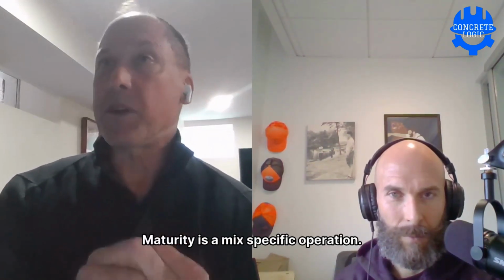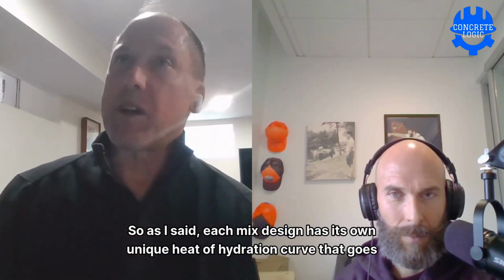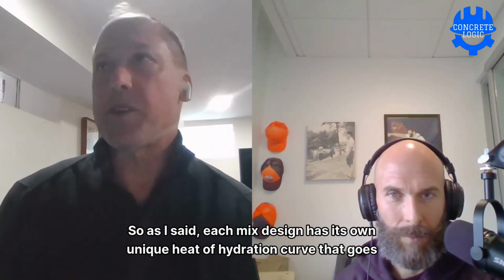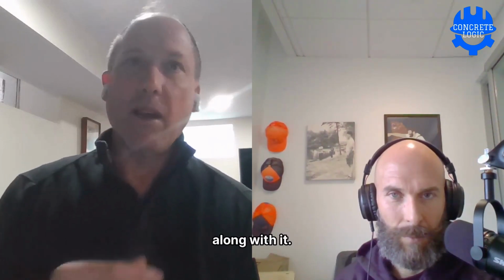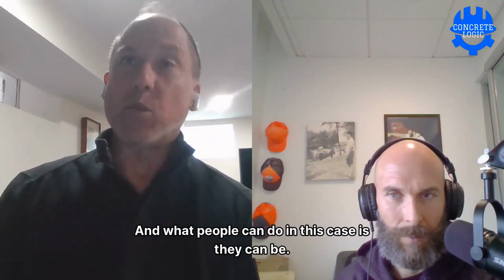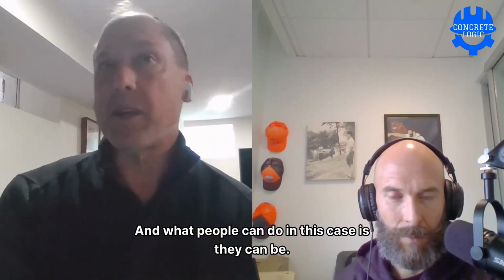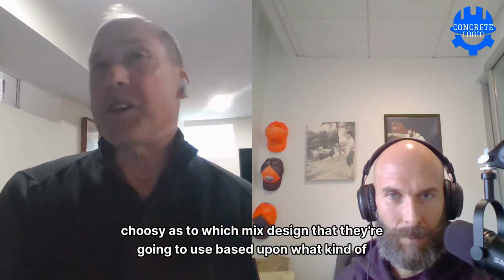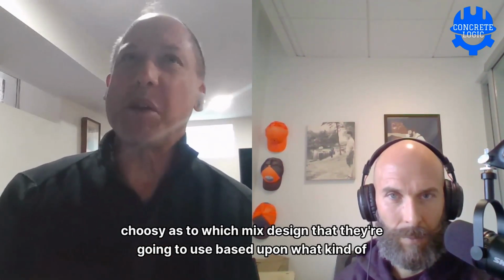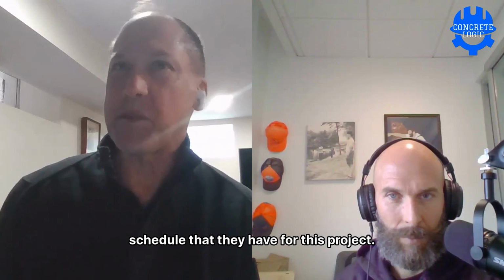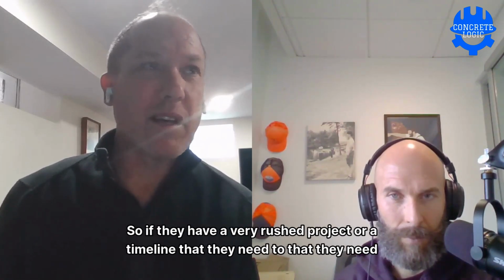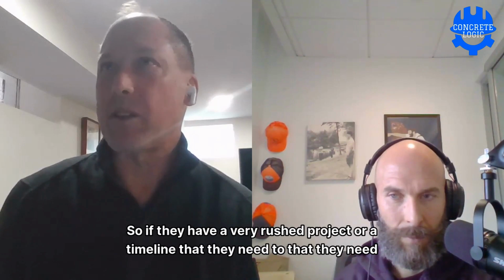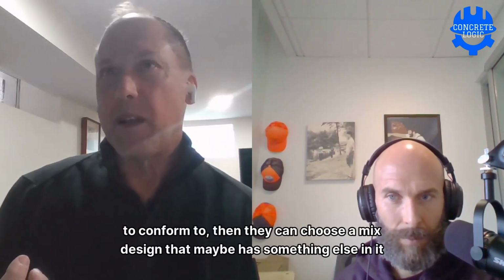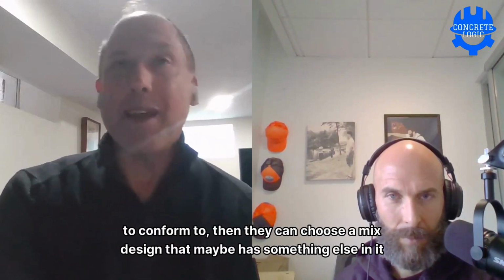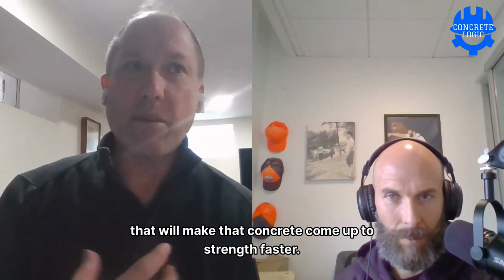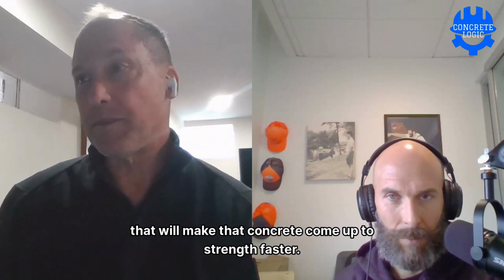Maturity is a mix-specific operation. As I said, each mix design has its own unique heat of hydration curve that goes along with it. What people can do in this case is be choosy as to which mix design they're going to use based upon what kind of schedule they have for this project. If they have a very rushed project, or a timeline that they need to conform to, then they can choose a mix design that maybe has something else in it that will make that concrete come up to strength faster.